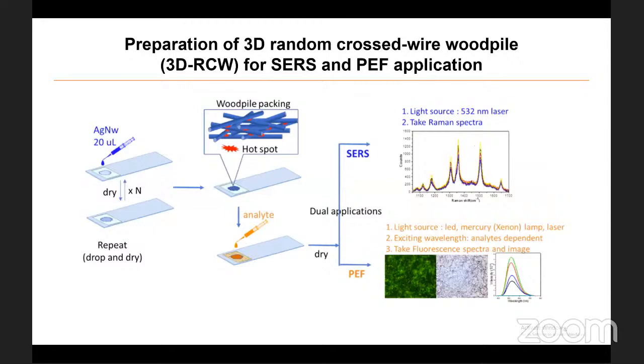We sprinkle a specific amount of the synthesized nanowire onto a glass slide and let it dry. The sprinkle and dry steps are repeated until wood-pile packing is formed, thus creating a three-dimensional random cross-wire wood-pile nanostructure. The wood-pile nanostructure can have many 3D hotspots, which can enhance Raman scatter signaling from the probe molecules. And with the analyte on this 3D RCW platform, we proceed to SERS and PEF analysis.